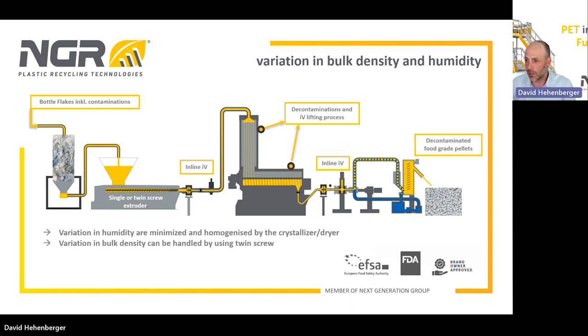Here you can see our bottle-to-bottle process. So we are going with pre-drying and/or a crystallizer into a single or twin screw extruder, depending on the moisture content and the bulk density. So compensating for bulk density and humidity is more or less our part, what we take care of and can handle by designing the system accordingly.